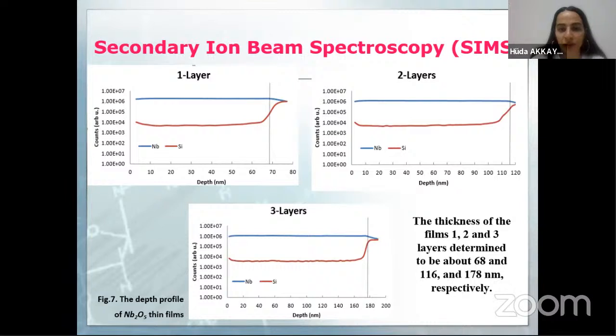Besides, we determined the niobium pentoxide films' depth profile: for 1 layer 68 nanometers, for 2 layers 116 nanometers, and for 3 layers 178 nanometers, respectively. And we conclude that as the layers increase, the amount of niobium pentoxide material increases.